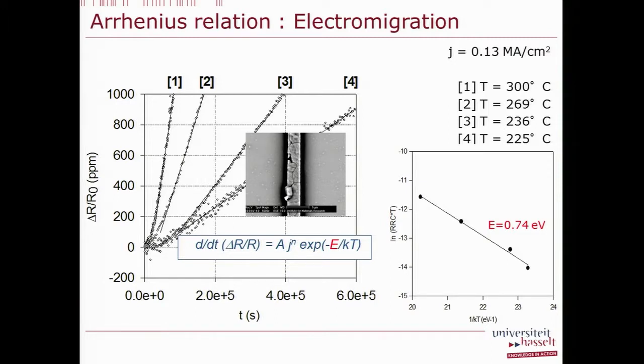But the nice thing is, for all these measurement points, we were able to really make a nice fit using this model, where we have the temperature that is related to this degradation with this activation energy. From these measurements, you can determine this activation energy. As mentioned before, it's a crucial parameter for lifetime predictions. So this is a kind of approach. Certainly if organic solar cells or organic-based solar cells are moving to more stable solar cells with smaller degradations, these types of Arrhenius approaches can be meaningful for the future.